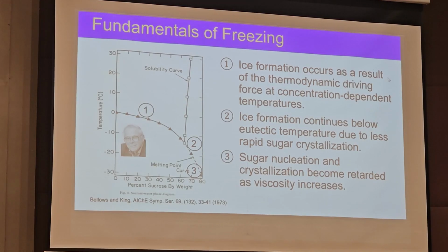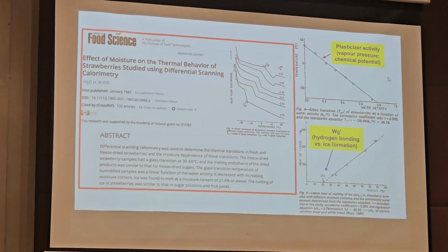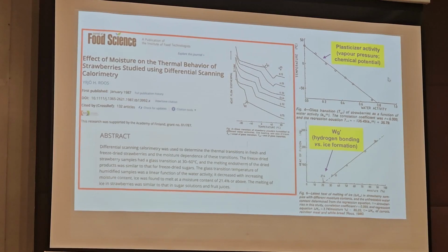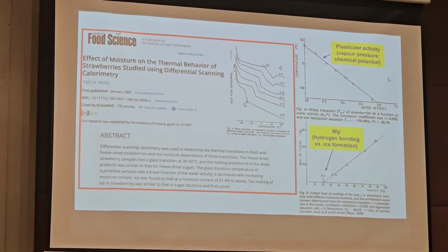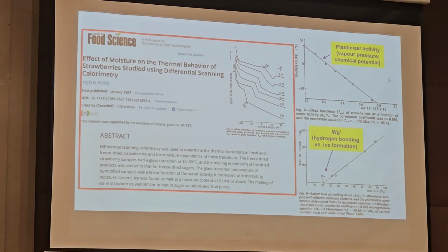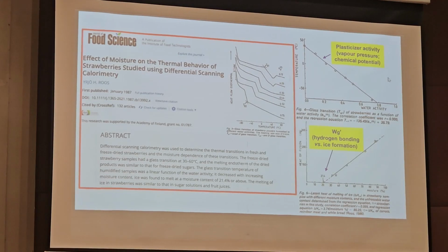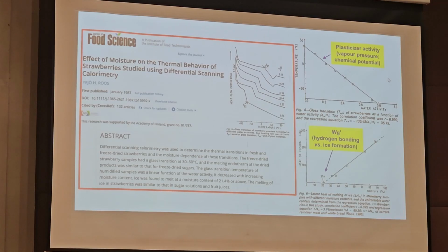So then the system is retarded, and what has been done is some of my early work here on strawberry substance, because we were trying to see how freezing happens in real systems, and we used the differential scanning calorimeter that is quite normally used to look at dynamic changes in samples. So we could see that if we have this water, we have the glass transition moving to higher temperatures the more water is frozen, or if the water activity of the system goes higher, the glass transition moves upward to a higher temperature.